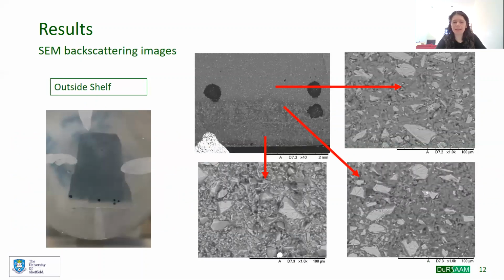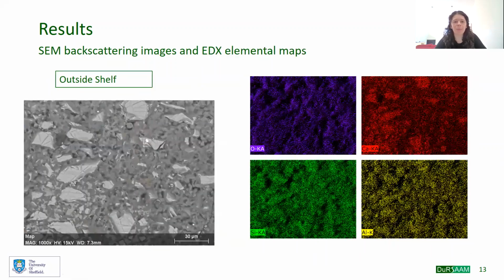I also did some SEM analysis, and we can observe that for the sample protected from the rain, the oxidation front is slightly different from the carbonation front, and the carbonation front seems to be pretty big. After zooming in on this image, we can observe that the carbonated part has some pore dropping and a lot of crystals, which are probably calcite or vaterite. And we can also observe white dashes within the carbonation front part, which is weird. So I did some EDX elemental maps, and we can observe that these white dashes are actually high in calcium, but we don't know yet what they are. It needs more analysis.